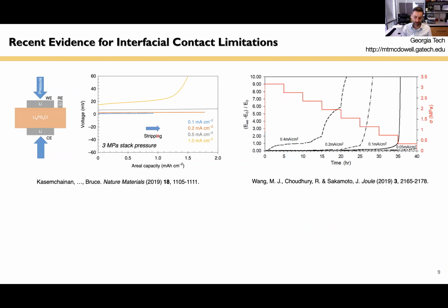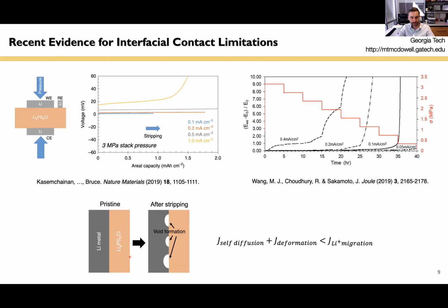All right, so I'll start here with the first segment on using synchrotron X-ray tomography to understand interfacial contact loss at solid interfaces. So I'll start here by showing some other literature data from a few years ago now. These are 2 very nice papers in which they use electrochemical methods examining the lithium interface with various solid electrolyte materials, actually. So here we have lithium metal in contact with this same argyrodite solid electrolyte. I believe this paper over here uses a different solid electrolyte. But what both of these studies showed is that there's, from an electrochemical point of view, some evidence for fundamental contact limitations.